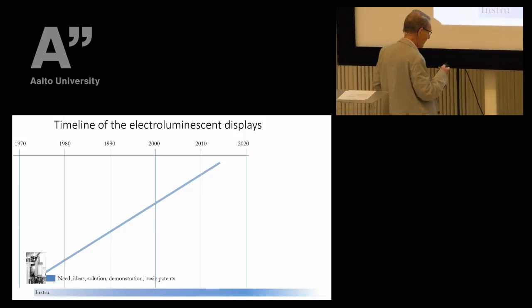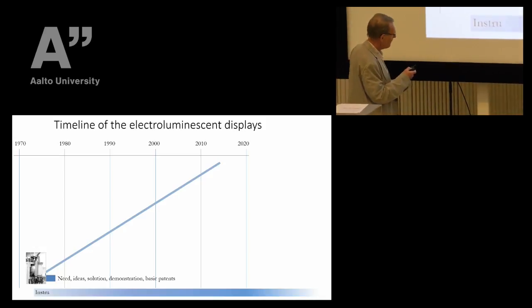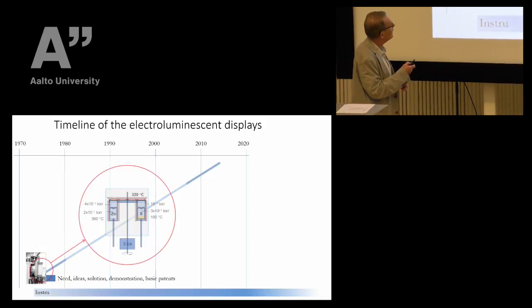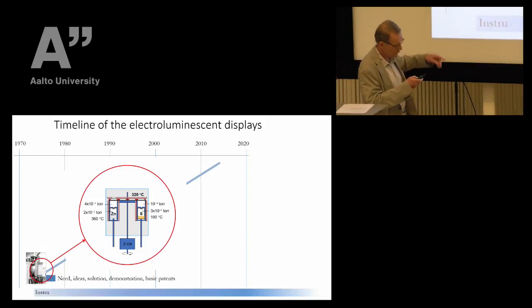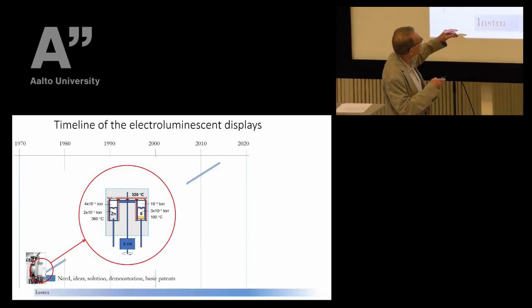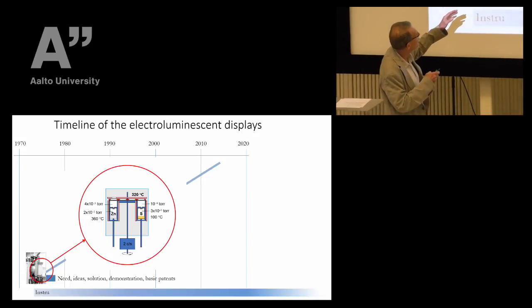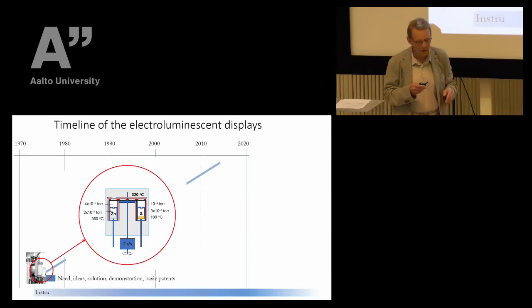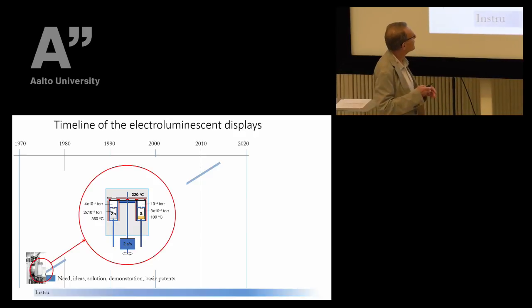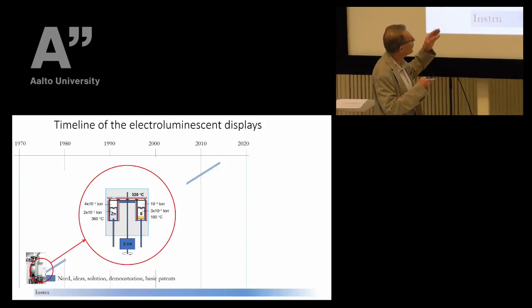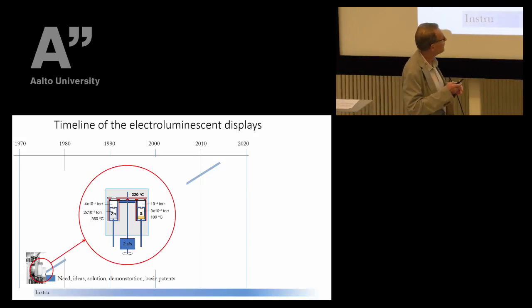So this picture here is the very first reactor. It looked like this, a vacuum chamber. And there's a rotating disc here, which makes the substrate see the zinc source here and the sulfur source here. It was rotated 2 cycles per second, so it was quite fast switching. And during the summer, when the construction was made, I calculated the necessary vapor pressures and temperatures in order to demonstrate the build-up of the material.